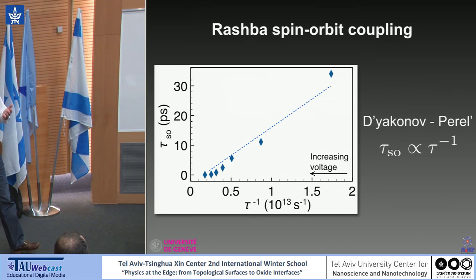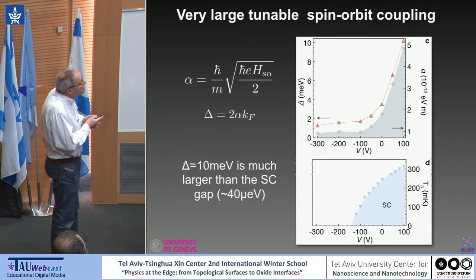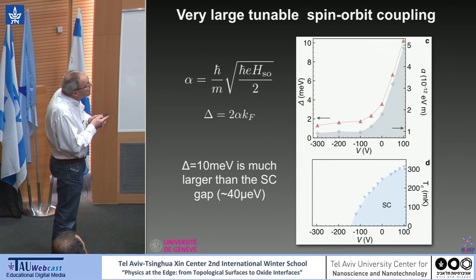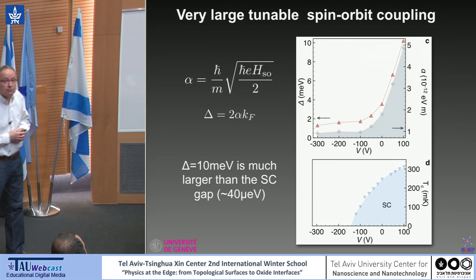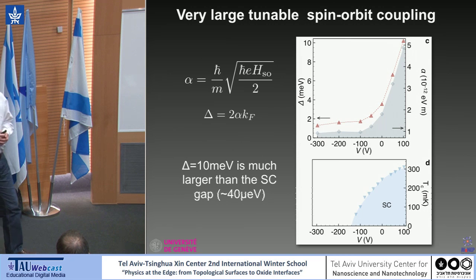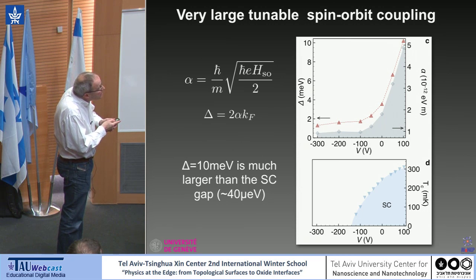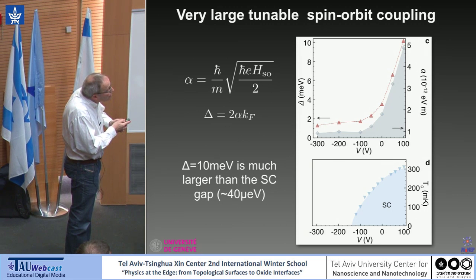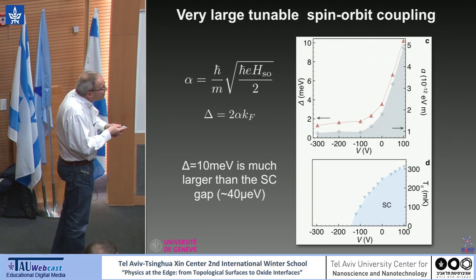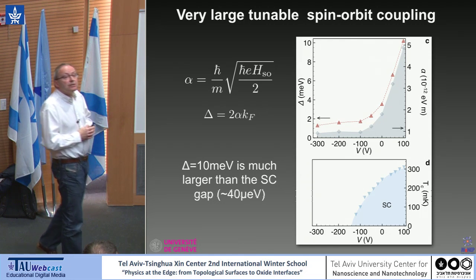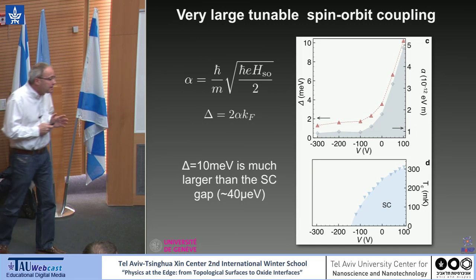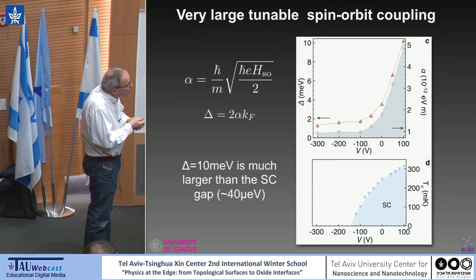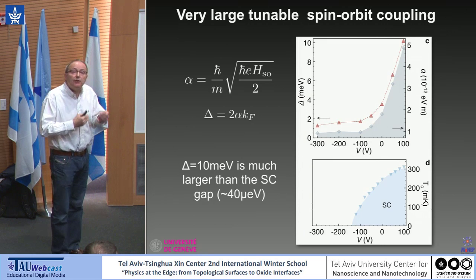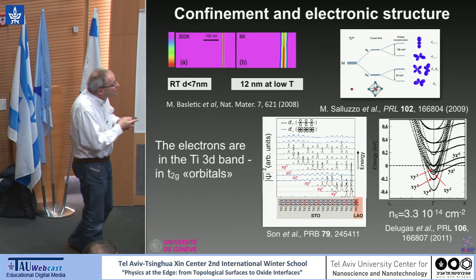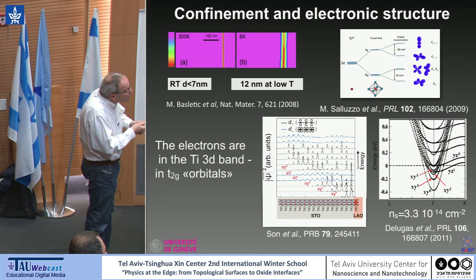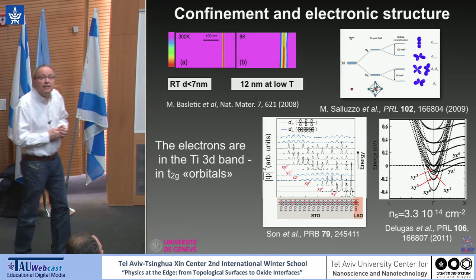So the spin orbit is important in the system, and its strength is increasing as you cross the phase diagram. The scale is a few milli-electron volts, which is much larger than the superconducting gap, which is 40 micro-electron volts. The doping range over which the spin orbit is taking off is very close to the doping range where we start to see superconductivity, and I will come back to this. What we believe is that this is the doping range where we start feeling the influence of the heavy bands, so we are very close to the xz and yz bands.